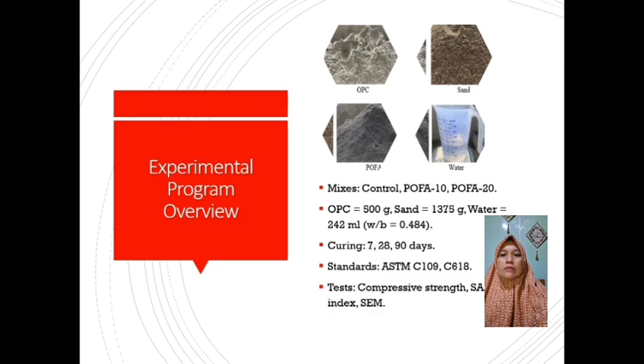Three mixtures were tested. The first, control, with 0% POFA, that uses 100% ordinary Portland cement, then 10% POFA and 20% POFA cement replacement. Specimens were cured for 7, 28, and 90 days.